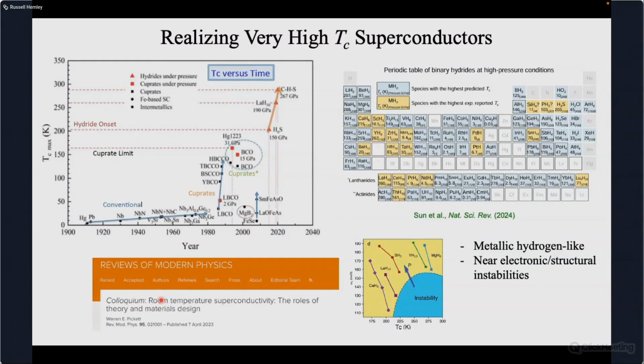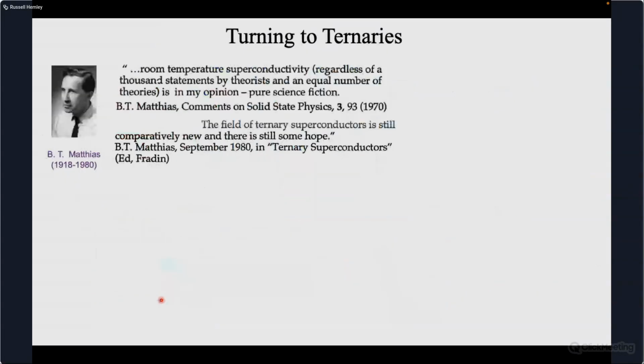And this is a very important point, because they're near instabilities, one really needs to go to a higher level of theory to treat them accurately. And this is a great challenge to theoretical calculations, as I'll show. So the binary problem is, in a sense, more or less solved from the standpoint of predictions of first order TC and showing quite high TC; the effects of magnetism and so on have been incorporated. Now, in going to higher pressures and looking for higher TCs, there's a focus on more complex systems.